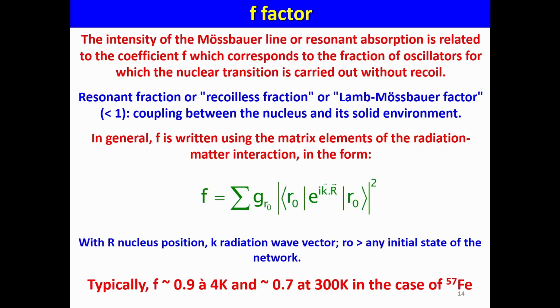Okay, I will not repeat all the first part in English, but now I speak in English. What I wanted to say before, in the case, for example, of tin 119, the F factor at room temperature is about 0.4, and it is about 0.8 at 77K and 0.9 at 4K. That means, to reply to the comment of Julian, we can have at room temperature, for example, 60-40 for two components, in the case of tin 2 and tin 4. But at 77K, you can observe the opposite. So you can easily distinguish, and you can have a strong difference between room temperature and 77K.